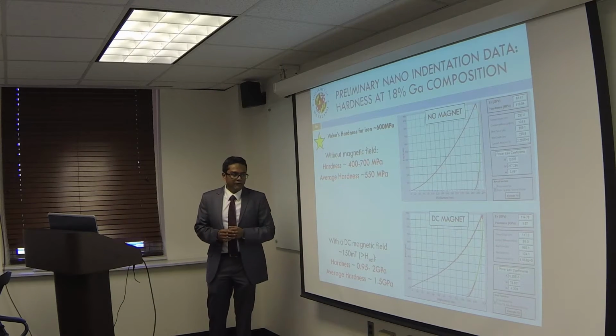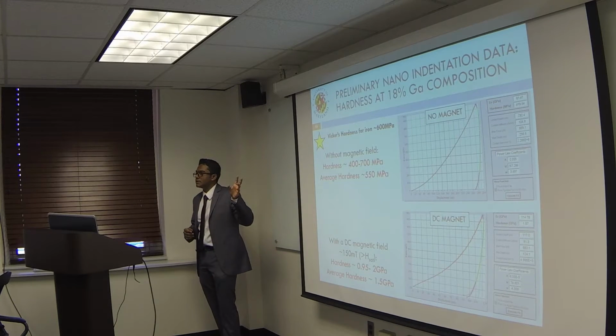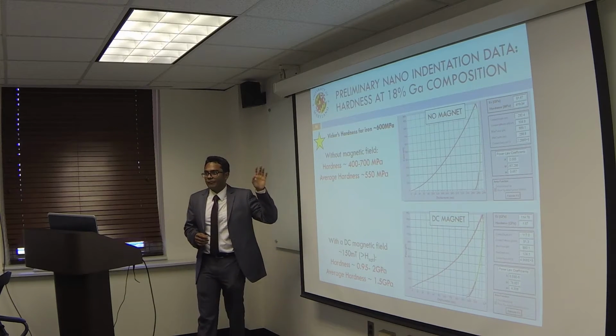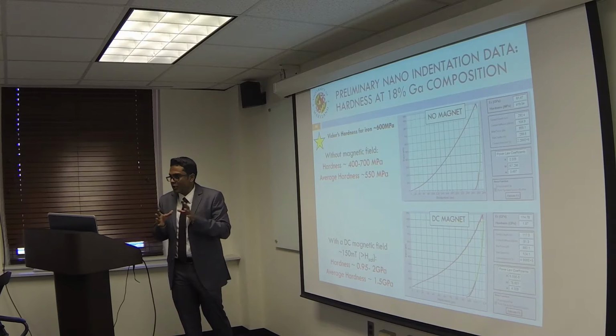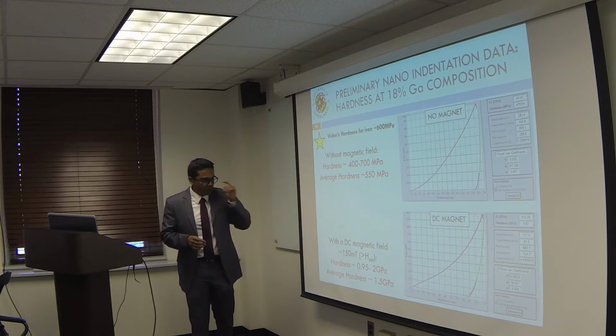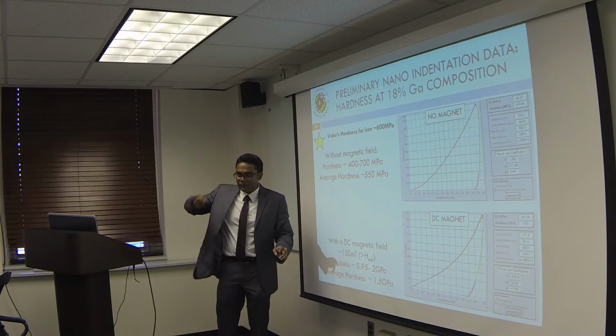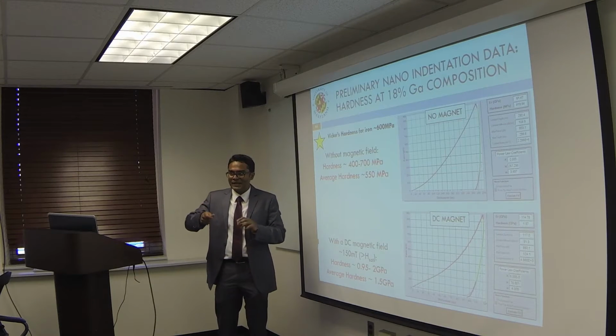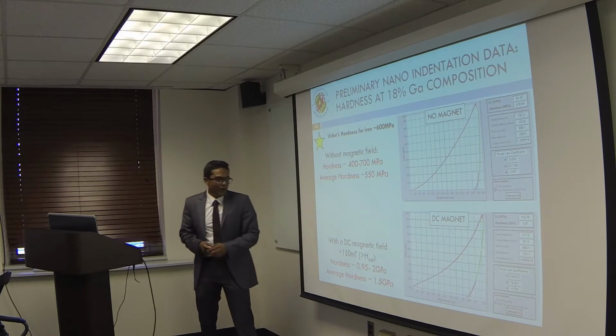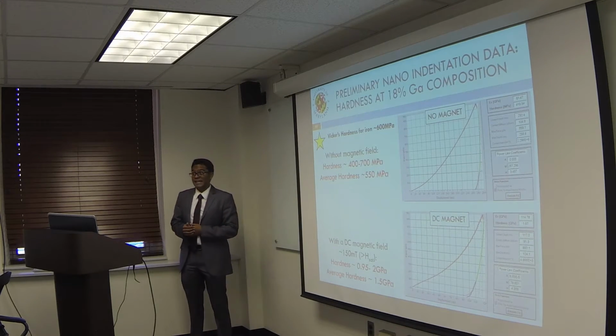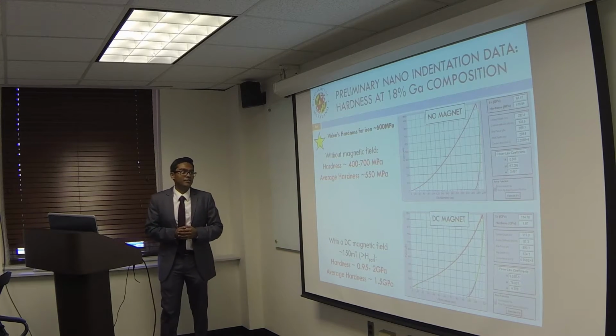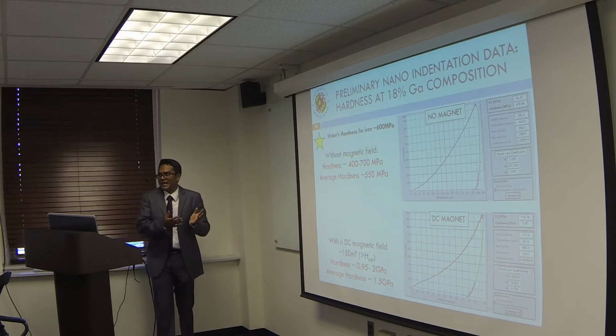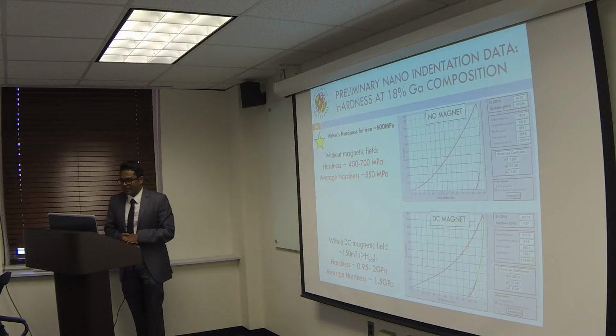But when we applied a magnetic field, this was done on the 18% gallium sample, where the value of Poisson's ratio at magnetic saturation was the closest to -1. When the value was closest to -1, and I put a bias magnet right next to it, and then indented it, the value went up to around 1.5 gigapascals, which is 3 times larger than what I was getting without the applied magnetic fields.